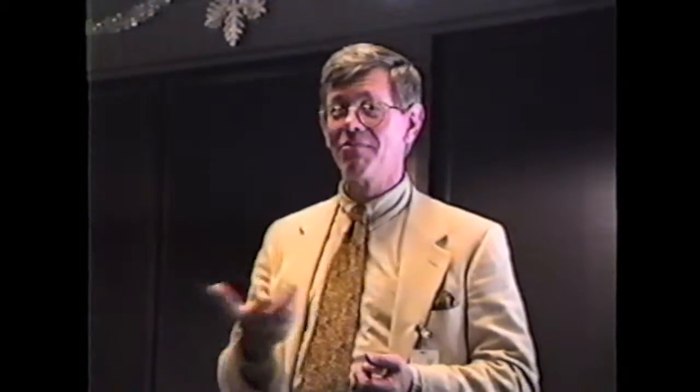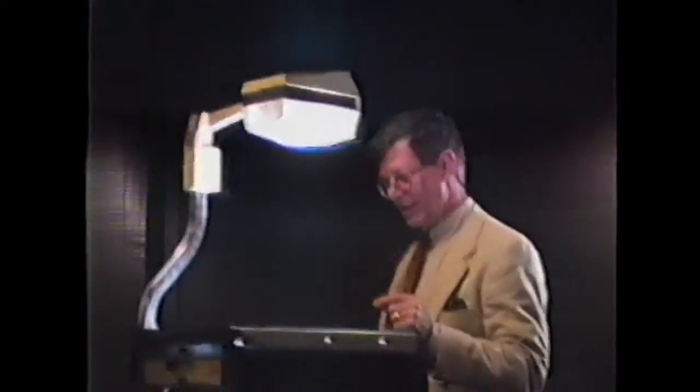The idea that they had was that normal hexane goes down these parallel channels and has a preferential end-on collision with the platinum, and then you get 1,6 ring closure. Now the problem with that is if you look at normal hexane and its conformers, it could easily ball up and just move down the channel any way it wants. There's no reason why it should hit end-on. And so that doesn't look very convincing. Eric de Rooyen had another version of this, which he called preorientation, where the molecule nests in the zeolite and starts to curl around on itself. That wasn't very convincing either.